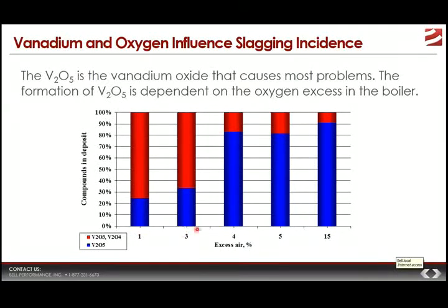What you can see clearly is that when excess air is low, like 3% or below, the blue, the amount of V2O5, the problematic one that's formed, stays relatively low. The red, which are the V2O3 and V2O4, are predominantly the majority of that compound. But when the operator finds themselves having to increase the excess air to 4% or 5%, it doesn't get up to 15, this is just for reference, but the more they increase the excess air, the more V2O5 is formed. And that is the one that causes the most problems.